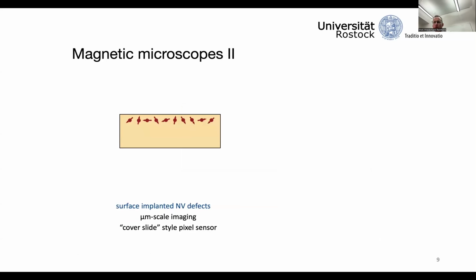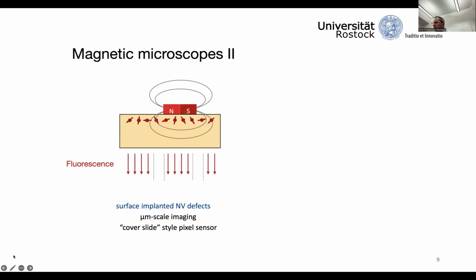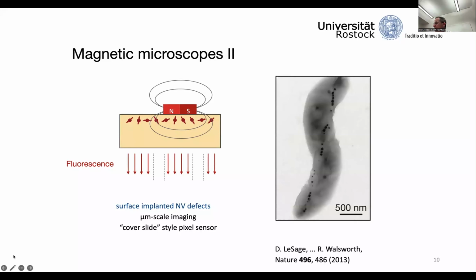This technique has also been used for imaging, where again, we can implant NV centers close to the surface of a diamond, and we can implant them in large quantities so that we can no longer discern a single NV center. Essentially, such a densely doped diamond surface is a kind of smart cover slide that translates magnetic fields into fluorescence, and that we can image in a microscope. So a magnetic field on the surface of such an imaging sensor will affect the spectral lines of the underlying NV centers. These spectral lines we can turn into fluorescence, and by that we can image magnetic fields. This has been used in particular by the laboratory of Ron Walsworth, formerly at Harvard, now at Maryland, to image magnetic inclusions in bacteria at the microscale.